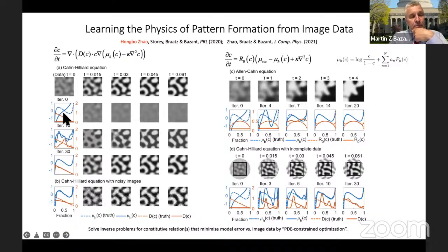Now, in the second row, we see what happens if we try to do a simulation starting from a model which is not phase separating. So we take the initial data and we end up basically erasing that and getting completely wrong results. But if we apply a certain mathematical or computational procedure, in this case, so-called PDE-constrained optimization, where we try to essentially find the partial differential equation that best produces simulated images that match the true, or known, images, to minimize the least squared error, essentially.